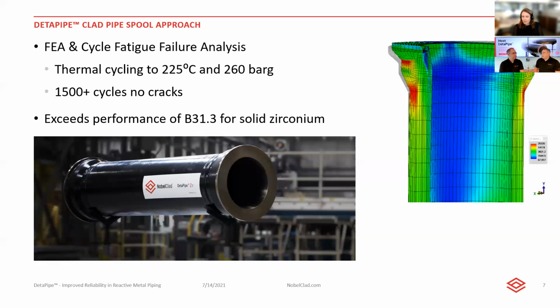In pipe fabrication, you can technically make it out of DetaClad, but it's got to be a large enough diameter that someone can get in there and actually do the weld, and you can do the inspection. It's not going to have any issues. But secondarily, if you have any issues with erosion, the proud batten strip to the surface of the cladding could also create another erosion failure site. So that would not be good. So yes, technically you can make DetaClad into pipe at 30 inches and above. Anything less than that would probably be unsafe and probably not suitable. Understood.